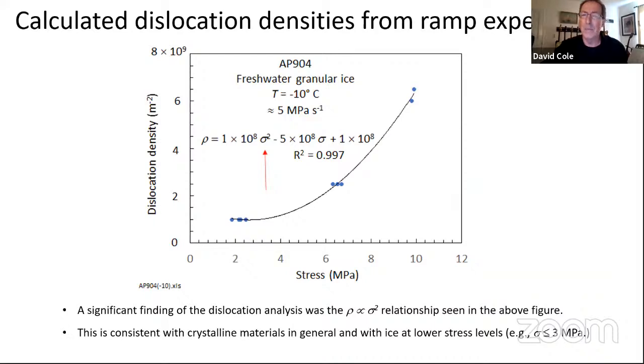But as I said before, I don't have this relationship nailed down for fast loading, but this is a very encouraging observation that the dislocation density is increasing, not only as we see at lower stresses in ice, but this is a generally observed relationship for polycrystalline materials in general. So that's all very encouraging.